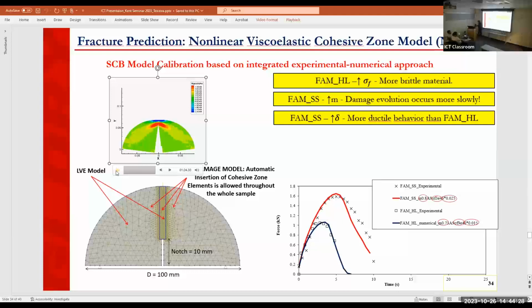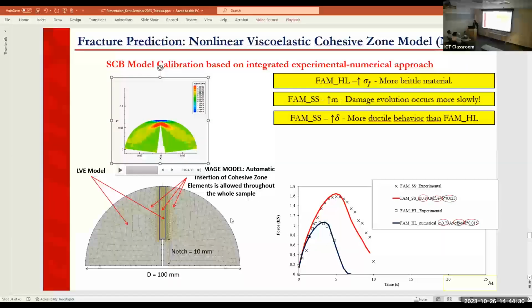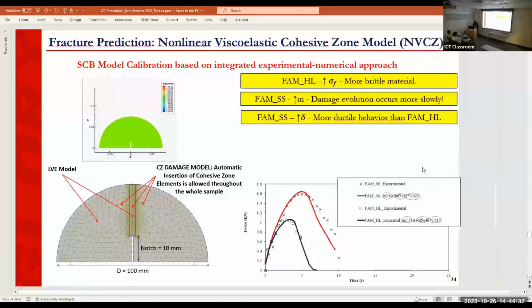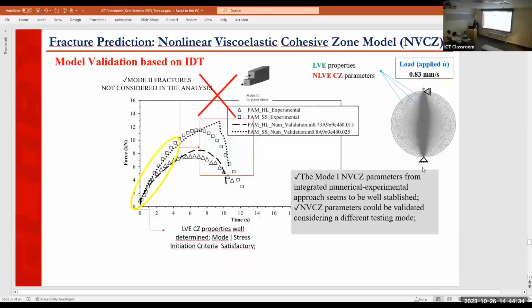Now using those same parameters, we simulated the IDT test using the parameters from SCB and the frequency sweep test. So we could get a good prediction. Now we can call this a prediction because we didn't calibrate. We used parameters from SCB and from the frequency sweep test, and we got a good correlation on the curves.